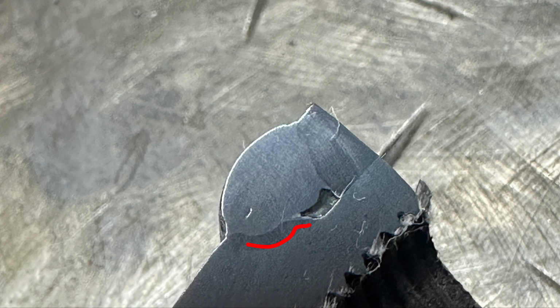And when you look at this, the weld itself actually bit into the 3/16 material of the tube far better than the thicker material, and that's very common with MIG.